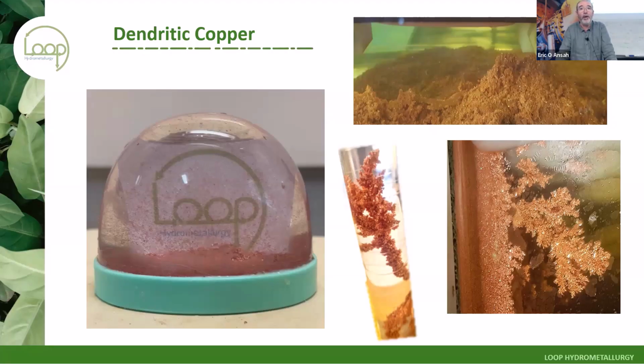So when I say that we can operate at a notional current density of 2000 amps per square meter, by keeping a constant presence of copper dendrite on our cathode, we're keeping a much higher effective surface area. I'd love an academic to tell me how I would measure an effective current density in this environment, but the short version is we are estimating that our actual effective current density would be sub 25 amps per square meter, even if we're notionally putting in 2000 amps per square meter of current.